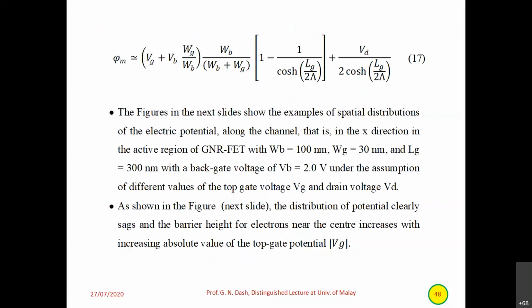So, actually, by big equations, nothing to convince, and they have been plotted, and seeing the graphs, we can conceive something. The figures in the next slide show an example of spatial distribution of electric potential along the channel, that is in the x direction, in the active region of the GNRFET, with the parameters specified here, under the assumption of different values of the top gate voltage and drain voltage V_D. As shown in the figure in the next slide, the distribution of potential clearly sags, and the barrier height for electrons near the center increases with increasing absolute value of the gate potential.